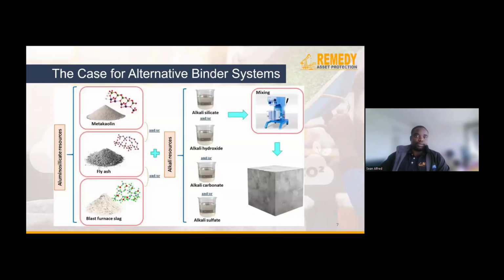Now, beyond just a Portland cement or general purpose cement, I'll specifically focus on alkali activated materials, which are a class of inorganic binders that are produced by reacting an aluminosilicate source material with a highly alkaline solution. And the source material is typically an industrial byproduct or natural material rich in non-crystalline or semi-crystalline aluminum and silicon. For example, fly ash, ground granulated blast furnace slag, metakaolin, and other materials like rice husk ashes and mine tailings.